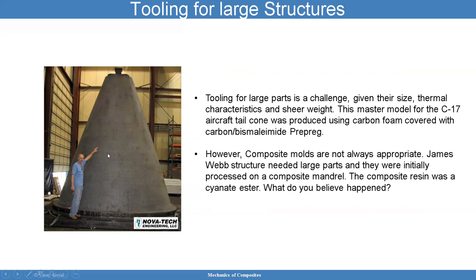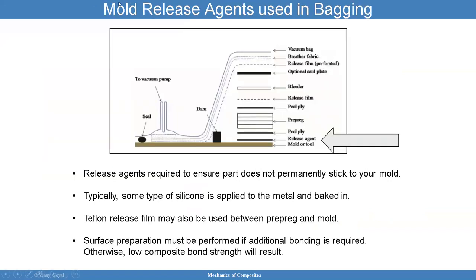However, composite molds are not always appropriate. The James Webb structure needed large parts and they were initially processed on a composite mandrel. The composite resin was a cyanate ester. Do you know what happened there? Why don't we think that through. Mold release agents are used in bagging.